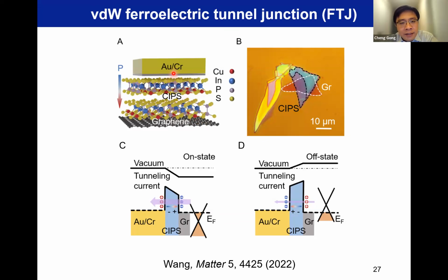The third one is the asymmetry between these 2 electrodes is really large. Conventional 3D metal and 2D metal, and especially these ones, the energy level chemical potentials can be easily controlled. If you have 2 similar conventional metals, chromium gold, chromium nickel, whatever, such a difference is not as large as these 2. So this electrode asymmetry is another reason.